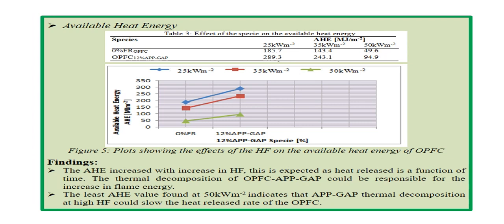Available heat energy. Figure 5 shows the effects of the heat release rate on the available heat energy of the oil palm fiber composite. The graph shows an increase in available heat energy. The available energy increased with increase in heat flux. This is expected as heat release rate is a function of time. The thermal decomposition of oil palm fiber composites, the ammonium polyphosphate, and gum arabic could be responsible for the increase in flame energy. The least available heat energy value found at 50 kilowatts per meter squared indicates that the flame retardant thermal decomposition at high heat release rate could slow the heat release rate of the oil palm fiber composites.